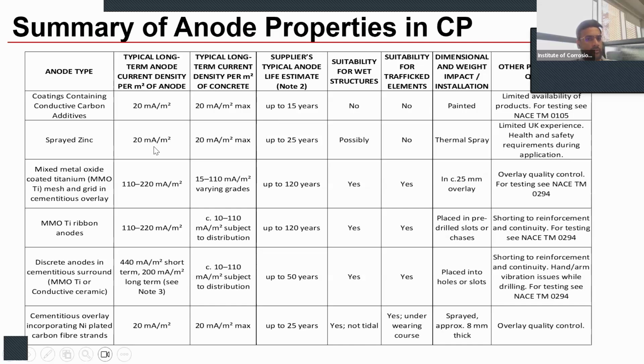Sprayed zinc, similar current density, can go up to 25 years. MMO mesh with cementitious overlay, a very high amount of current can be passed through it, about 110 to 220 milliampere per meter square, with typical anode life about 120 years. Similarly, for ribbon anodes, discrete anodes, again much higher life, 50 years typical. Then cementitious overlay with nickel-plated carbon fibers, 20 milliampere per meter square of concrete surface area, with typical life up to 20-25 years.